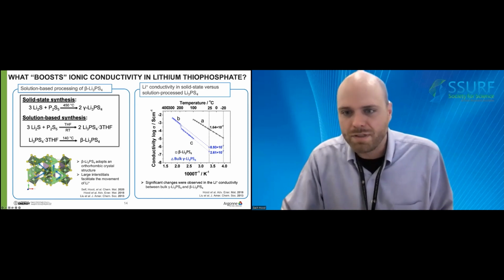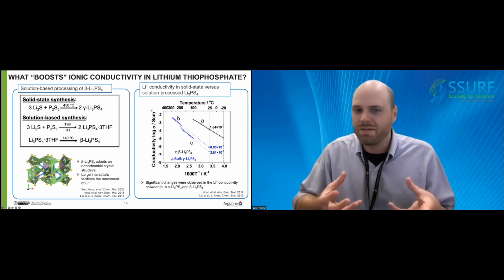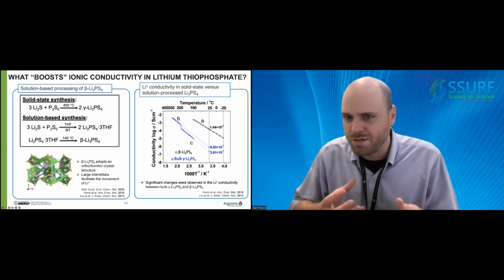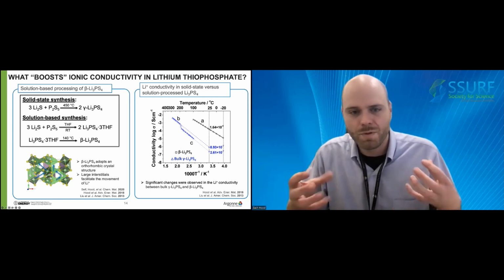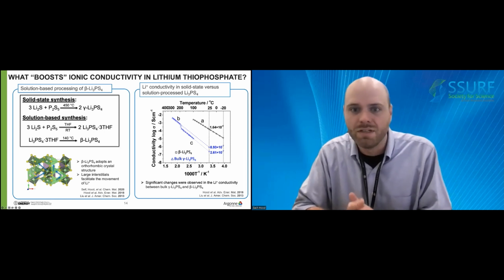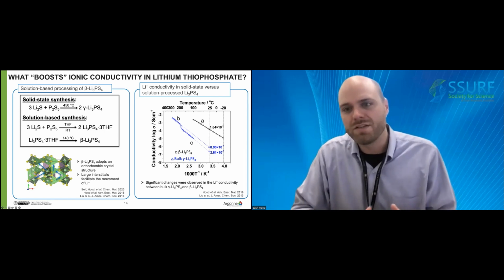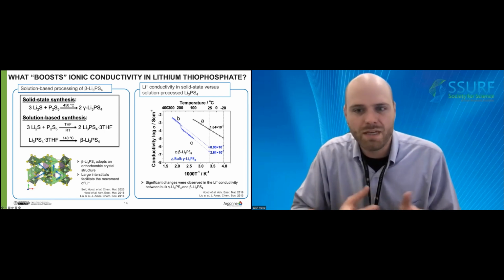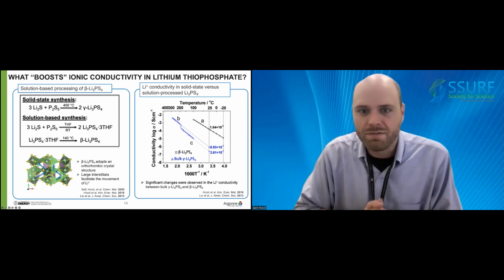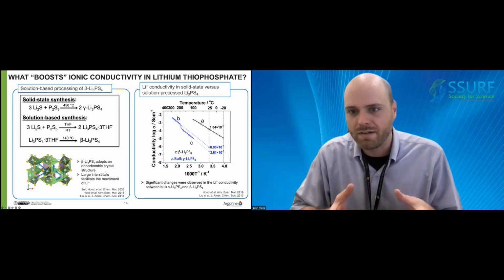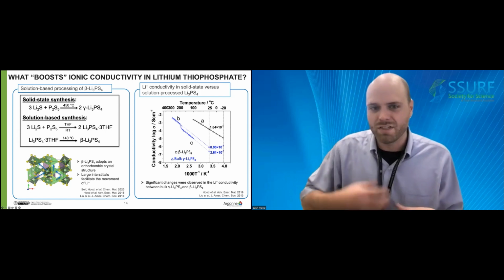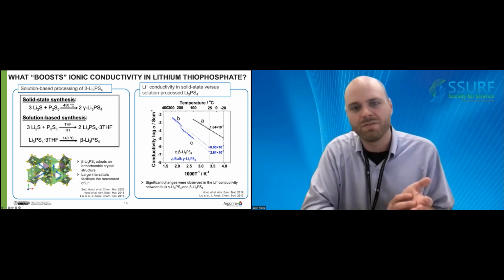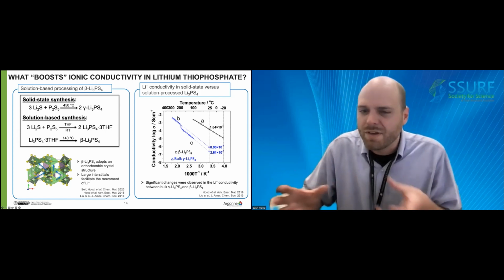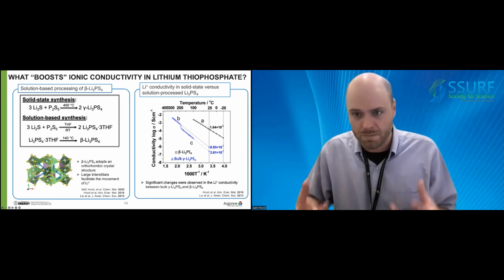While the reaction is relatively straightforward, we are generally left with co-crystallized solvent in the material that must be removed with heat and vacuum. And by doing so, we are left with the beta phase of the lithium thiophosphate with the PNMA space group. And if we take a look at the measured ionic conductivity of the bulk lithium thiophosphates versus solution processed lithium thiophosphates, we can see a significant difference in some of their properties, such as lithium ion